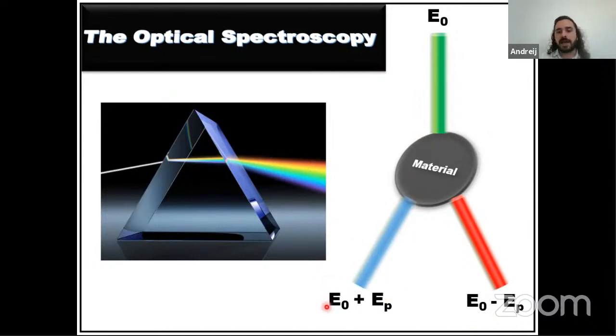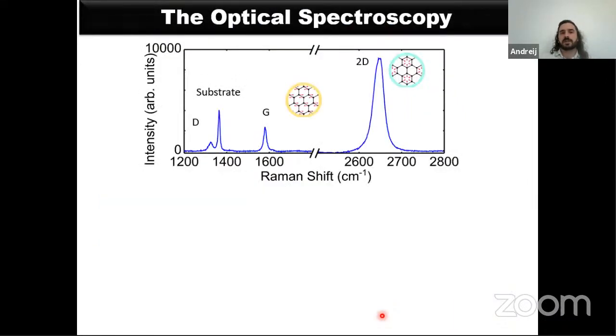here. This blue one has a larger energy than the initial laser, so E0 plus EP, and the red one has a lower energy, E0 minus EP. And this EP is very specific for each material. It's like a fingerprint. And in addition to just a simple fingerprint, the Raman spectroscopy gives very deep information on the materials. Like, for example, this is a very standard spectra from graphene, where we can see the D band is related to defects. We can see the peak from the substrate, and also the G band, which is related to the stretching vibration from the carbon atoms. Then we go to the 2D band, which is a second order process related to electronic structure, stacking order, and also to this breathing phonon vibration.